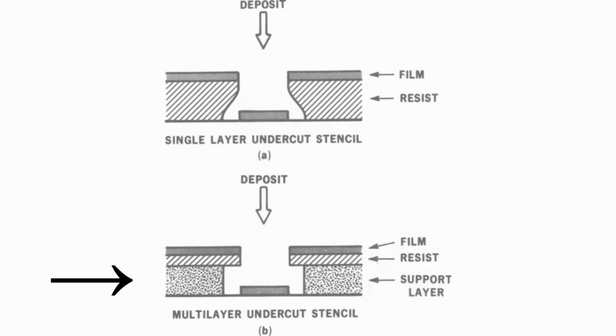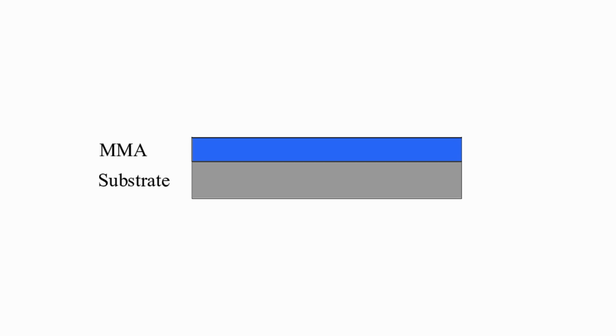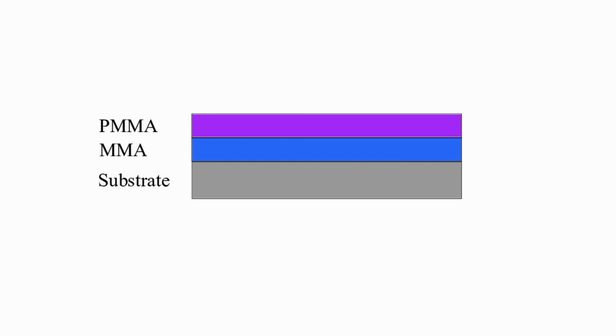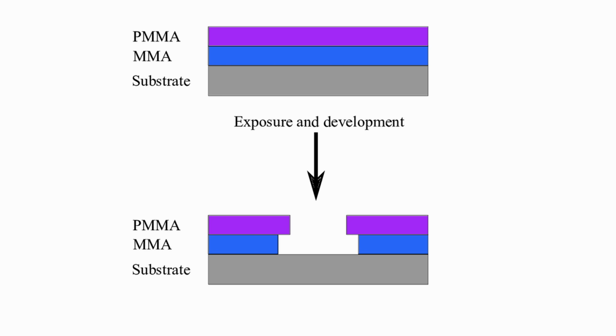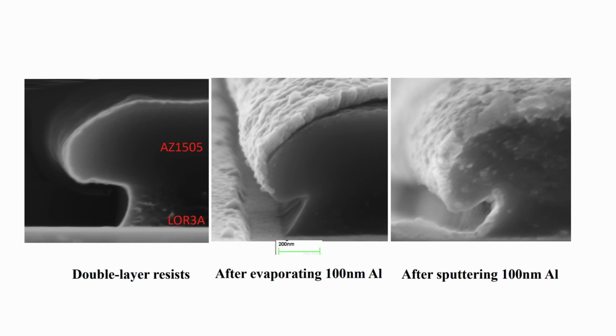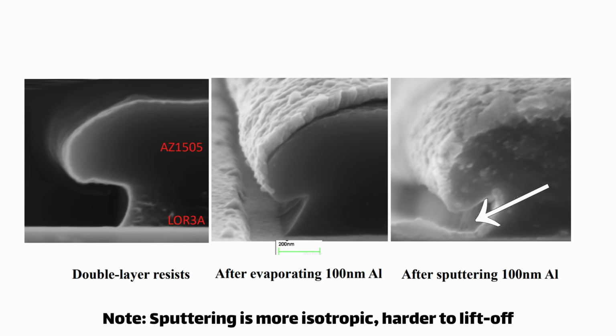There are a few ways to do this, but in practice, the easiest method is with a bi-layer process. So I'm actually depositing first a layer of MMA copolymer, followed by another layer of PMMA. The MMA dissolves slightly faster in the developer, leading to an undercut region. This undercut is unlikely to get coated with metal and provides a location for the solvent to start dissolving.